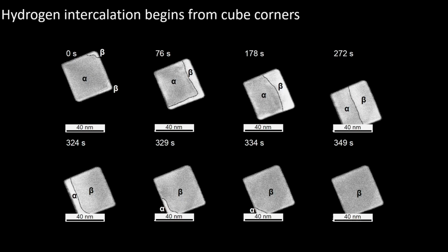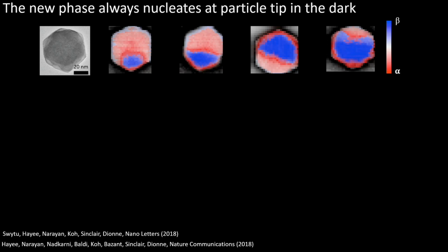And if we look at some still snapshots of that particular nanocube, we can combine both this direct imaging, which basically comes from dark field imaging and diffraction, with electron spectroscopy to confirm that the new hydrogenated phase, which I've labeled here as beta, basically starts at the cube corners. So it makes sense. Those low coordination number sites, those corners, are the most active sites for hydrogen intercalation. And then hydrogen intercalates into your nanoparticle, stabilizing along this 100 type interface until eventually the whole cube is hydrogenated.